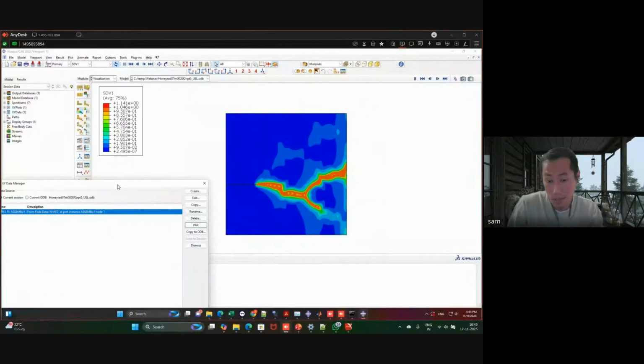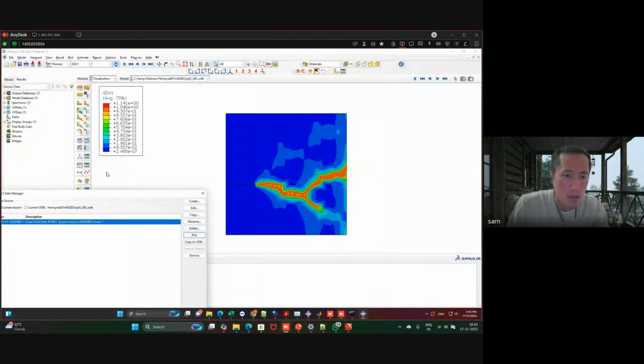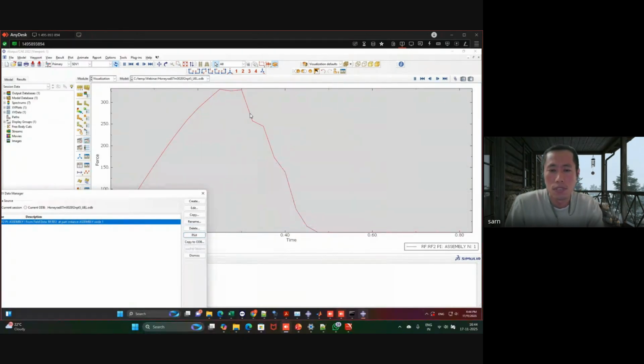the crack is not going on a straight path. It has to deflect when it comes across the hard region. While deflecting around the harder region, because of that, we can see the kinks on the load versus displacement plot. So this is a region where the crack is trying to avoid the hard phase or the hard region.